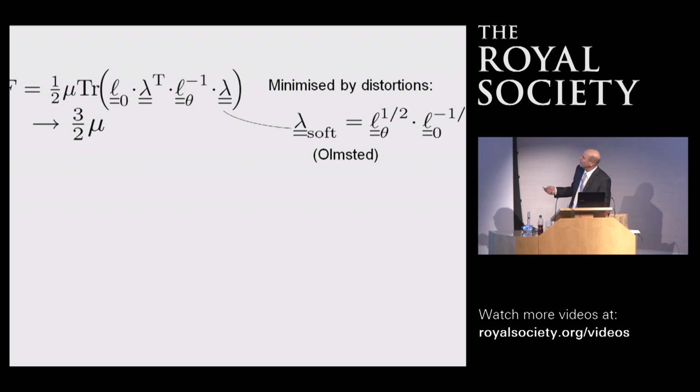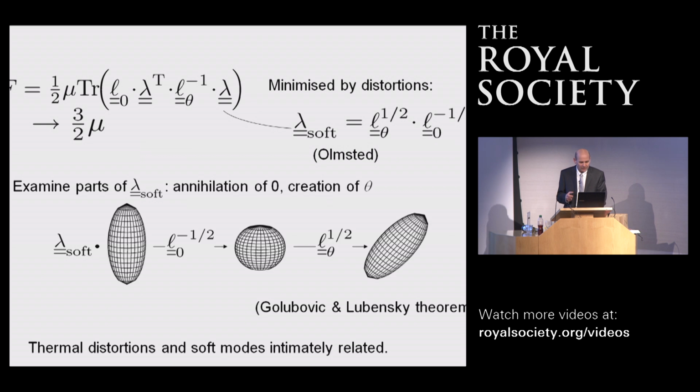So this is Hooke's law, and if I put this special deformation in there, then you will see that these square roots of tensors are annihilating on these guys, and the answer here is the unit tensor, and the trace of the unit tensor is 3. So the energy is just 3 times a half mu, the scale out the front. And that means that the energy hasn't changed from the original rest state, and so the energy indeed doesn't go up if it's distorted in this particular way. A very special way, essentially these shears and diamonds and so on that you saw on the previous slide.